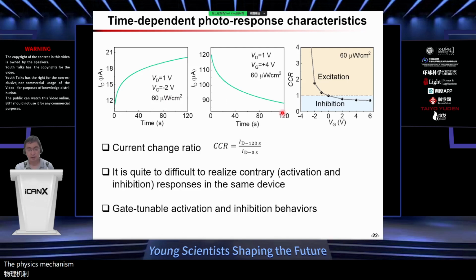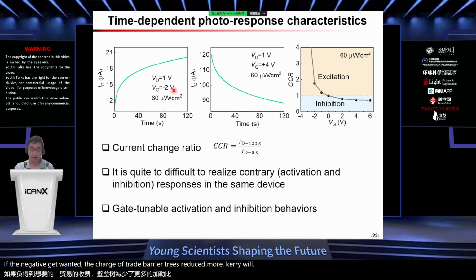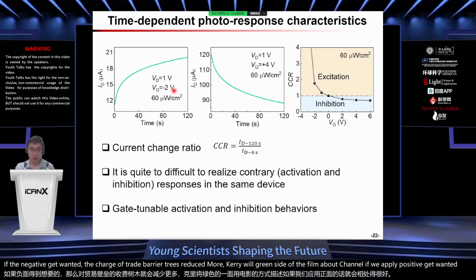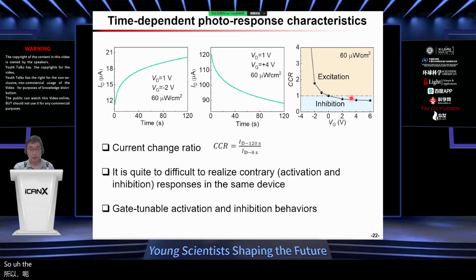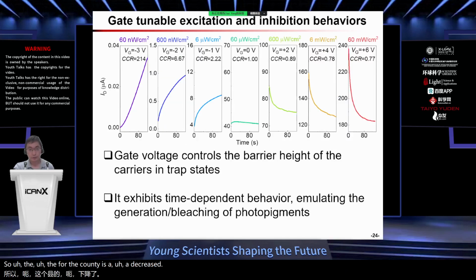The physical mechanism is very straightforward. Here we just use gate voltage to control the barrier of the interface charge trap. With a negative gate voltage, the charge trap barrier is reduced, and more carriers will go inside the semiconductor channel. If we apply a positive gate voltage, the barrier height is increased, so the photocurrent is decreased. By combining different gate voltages at different light intensities, we can use the same device to demonstrate activation and inhibition. That means we can do vision adaptation in both directions: we can decrease the sensitivity, and we can increase the sensitivity. It is very similar to the human retina, which consists of both rod cells and cone cells.